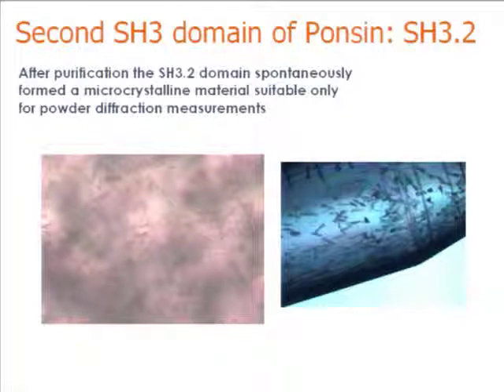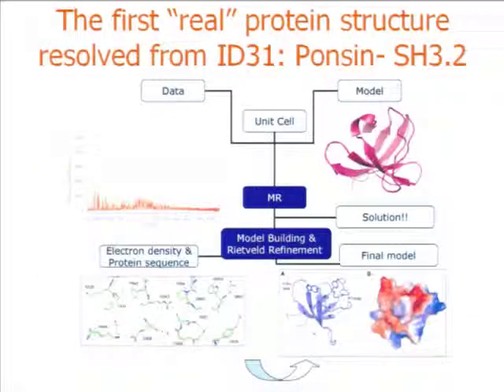They were needle-shaped microcrystals. So we collected various profiles at ID31. One of them is shown here. The data were indexed, and we could obtain a starting model of a 60% homologous protein from the protein data bank. We used this model to apply the molecular replacement method, and we could easily find the position and orientation of this model in the new unit cell.